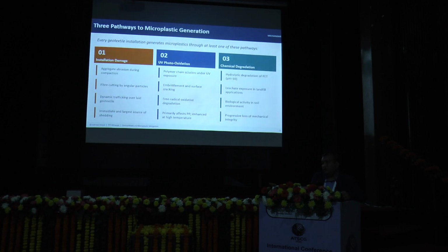Second is UV photo-oxidation. Whenever PP material is exposed to sunlight, UV degradation starts. UV rays cause chemical breakage of the bonds of the PP material, and during its whole life microplastic is released. Oxidation makes the material embrittled, with surface cracking and free radical oxidation. This generally happens. The UV problem is mainly in PP materials.